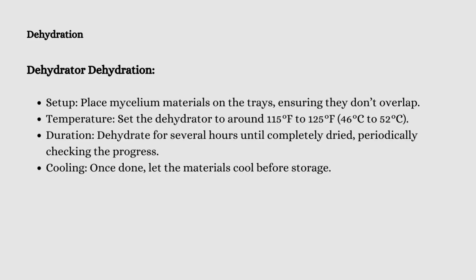And that's something to note also for these materials, these myco-composites. It doesn't happen as much as with the membranes because the membranes are just so much more thin and delicate. Yeah, the sides will curl in, so you'll likely lose some of your material if you try to dehydrate them quicker rather than wait the appropriate time and do it in a slower and sustained way. So faster is not always better, right?